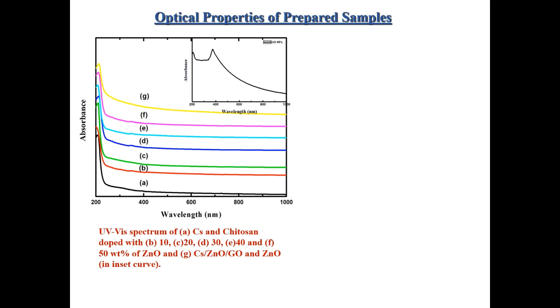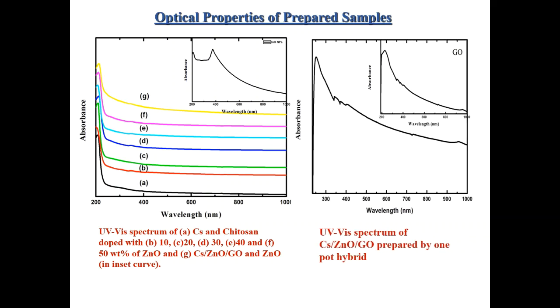The UV-visible spectra of chitosan doped with different weight ratios of zinc oxide, and of chitosan zinc oxide graphene oxide, showed a maximum absorption peak at 206 nanometers for chitosan. For chitosan zinc oxide, there is a shift in the peak of chitosan toward longer wavelength, according to the appearance of zinc oxide. The presence of pi delocalization along the polymer chain has been stated due to the strong shift toward longer wavelength, and there is a weak peak that appeared at 350 nanometers, which increased with increasing filler, indicating and confirming the interaction between chitosan and both zinc oxide and graphene oxide. Also, the one-pot hybrid composite showed an absorption peak at 252 nanometers, attributed to the interaction between chitosan, graphene oxide, and zinc oxide.